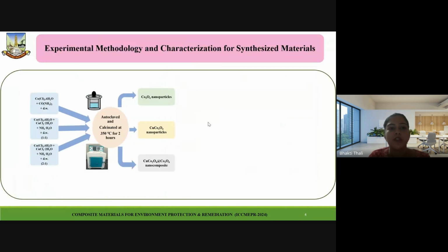So now I'm going to talk about the experimental methodology which I have adopted for the synthesis of all the materials. Firstly, cobalt chloride along with urea and distilled water was autoclaved and calcined to obtain the cobalt oxide nanoparticles. Further, cobalt chloride and copper chloride along with ammonia water and distilled water were taken in the ratio 1:1, autoclaved and calcined at 350 degrees Celsius to obtain copper cobaltite nanoparticles.